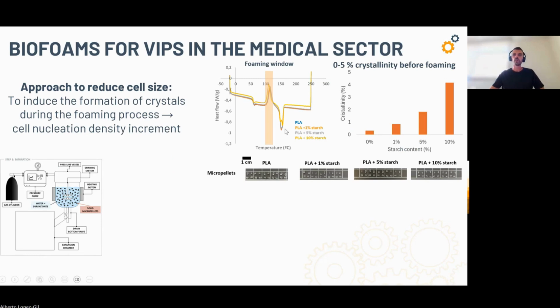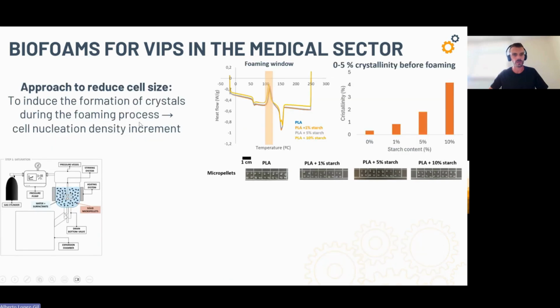And then we also needed to have nanocells in our final foam. So the approach we use is to induce the formation of crystals during the foaming process so that we could increase the cell nucleation density in the process. And we did this by foaming at a temperature below the melting temperature of the polymer. This is the DSC of the different materials, different PLA grades we use. And this is the foaming window we use.